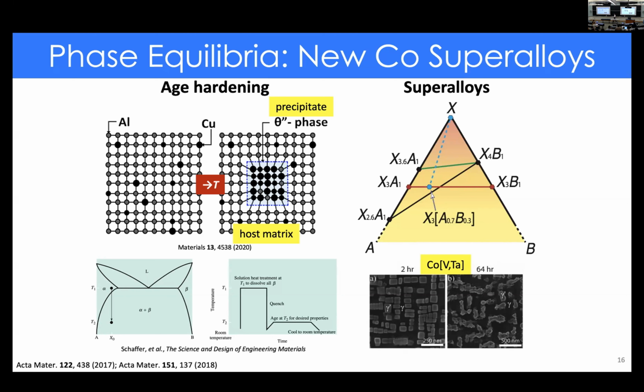I can't form that blue line. On the other hand, if the phase diagram has a facet that looks like the black line here, then there do exist a range of compositions, a narrow one, where you can have that tie line exist. By scanning all these different ternary phase diagrams for a descriptor that has this mapping, we're able to come up with a set of predictions of most likely candidates for new superalloys. Then in 2018, as I said, a group independently picked this up and was able to show this nice gamma prime structure, which is canonical for the superalloys.